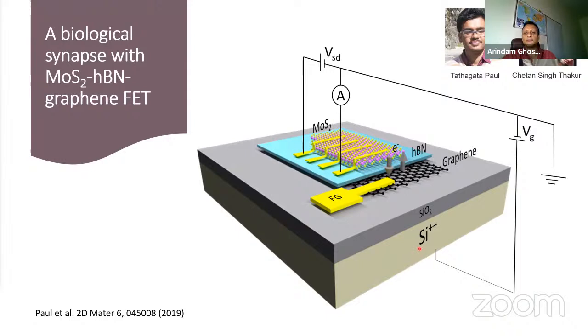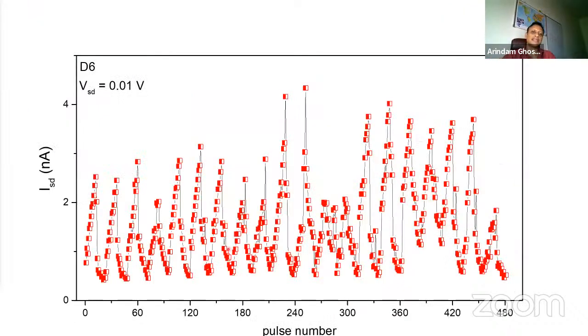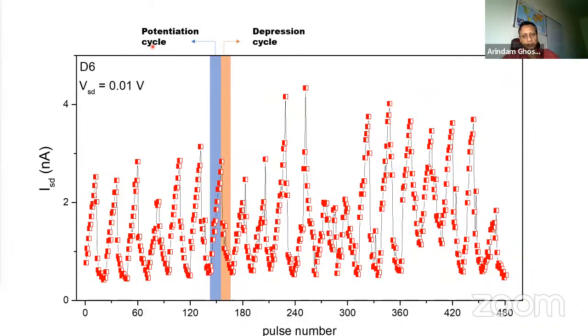What you do is that you give pulses to the gate underneath, and positive pulses store charge in such a way that it makes the channel conducting. And if you give opposite negative pulses here, then the charge essentially gets washed away, and the molybdenum disulfide layer becomes insulating. So these are the potentiation cycles and the depression cycles. You can see this is the large number of pulses that we have been able to give to the silicon gate. With every pulse, each red dot is a pulse on the gate, you can see the electrical conductivity increases, and then we give pulse in the opposite direction, and electrical conductivity comes down, the depression cycle.